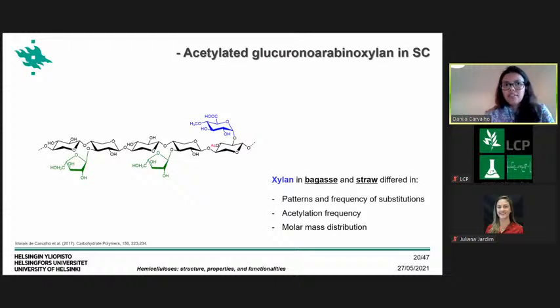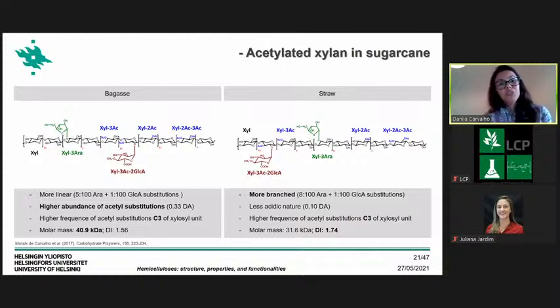What we could see from the results in this study was that it was possible to isolate acetylated glucuronoxylan from the sugarcane waste. But the structures of the xylan from bagasse and straw were quite different, with some variation between these different tissues in terms of pattern and frequency of substitution, in terms of acetylation frequency, and also the molar mass. Here I have the illustration of the structure that we could elucidate in this study. If this structure is too much information for you, please don't be scared, just focus on what is more important from this elucidation.